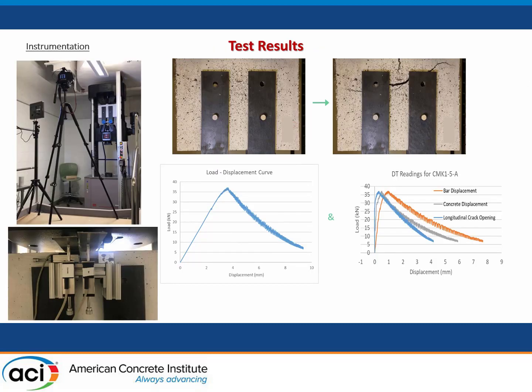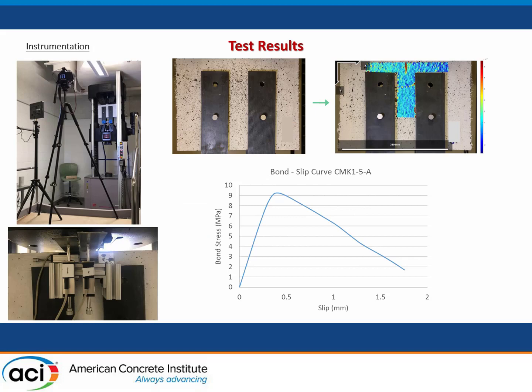The tests were done using both conventional measuring instruments as well as digital image correlation. In the bottom right figure, you see in blue the displacement of the concrete surrounding the bar. In orange, you see the bar displacement. So the difference between these two and the force developed divided by the contact area give you the typical bond slip curve that we obtained from all the various tests that we did.